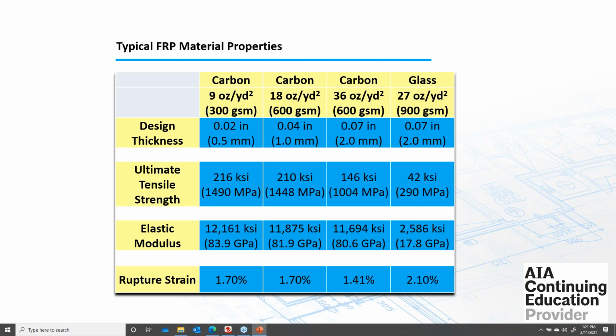So just kind of comparing some of the different products. I put some of the more traditional weights of fabric that you'll see. All the FRP products in the market are designated by a weight. The two most common that you'll run into are 9-ounce or an 18-ounce carbon, which is 300 grams per square meter or 600 grams per square meter. More recently, we've seen some heavier fabrics coming out. We have one as well. I've got a typo there, I apologize. It should be 1,200 grams per square meter on the third column and 36 ounces per square yard.